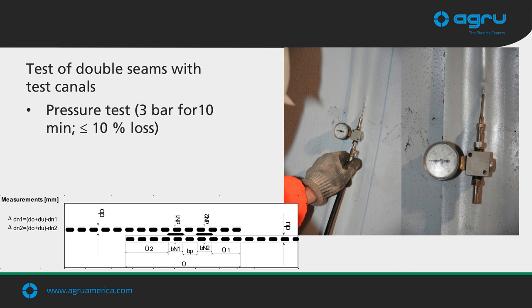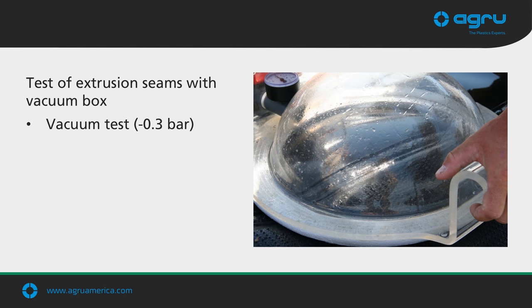The double wedge weld creates two welds with an air pocket in between that can be pressurized and monitored for pressure loss to confirm the weld is competent with no leaks. For extrusion seams or other detail areas where a double wedge weld isn't available, we vacuum box test — applying soap to the liner within the box, creating a vacuum, and looking for bubbles that indicate a leak.